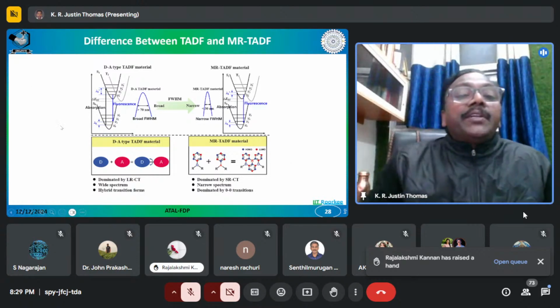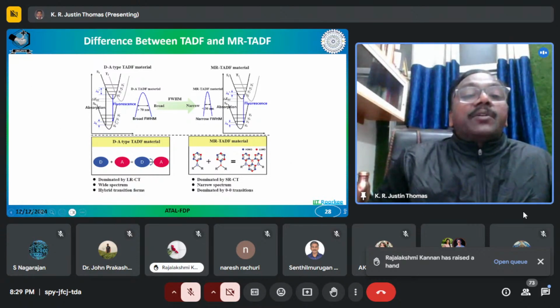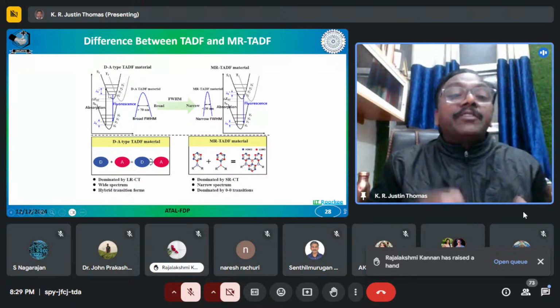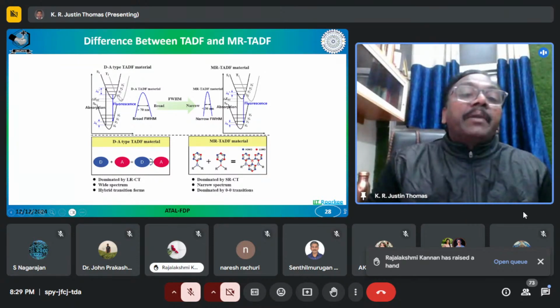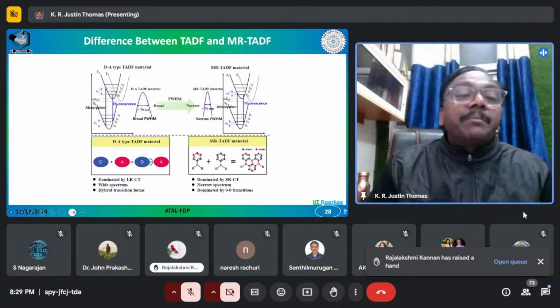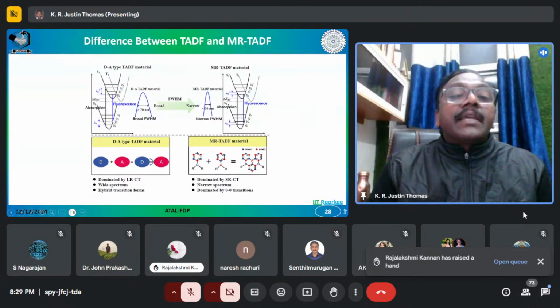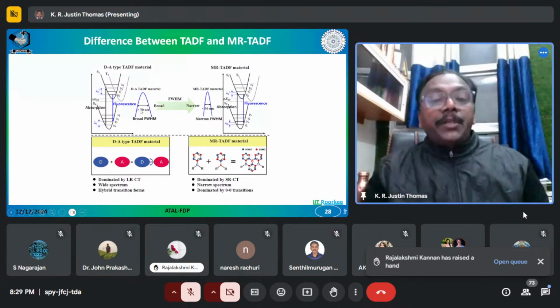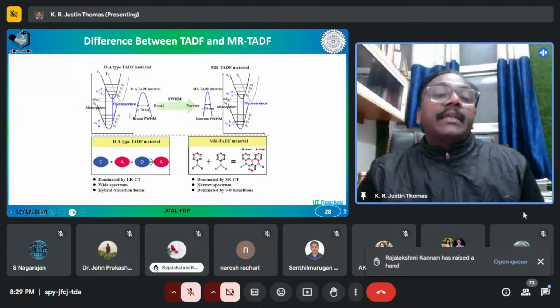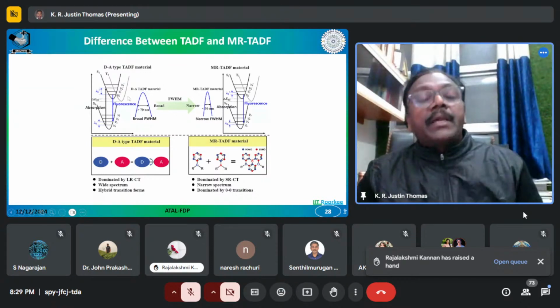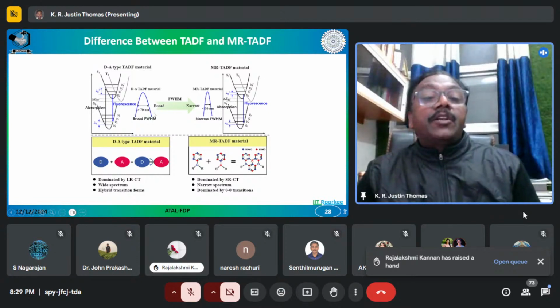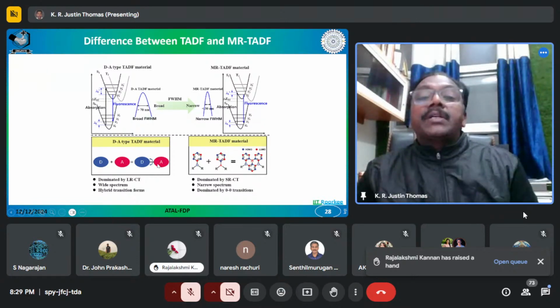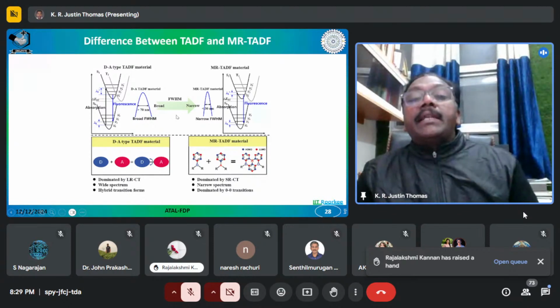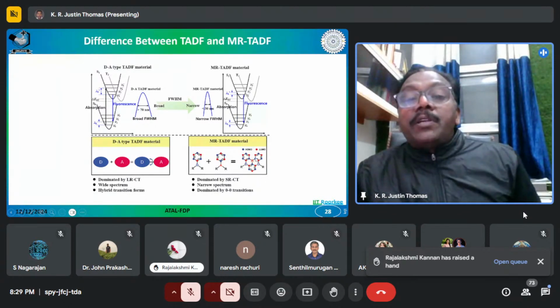So as I have shown here, you can see that the singlet ground state goes to the singlet excited state, which is showing a reorganization. So because of that, there is a very big Stokes shift. And then when the fluorescence is taking place from here, while the absorption is taking place from this vibrational state, you have a huge broadness in the emission. That is what will be a typical fluorescent molecule as well as a TADF molecule, which is having a donor acceptor structure. But when you go for an MRTADF material, now it's a rigid molecule, something like that.